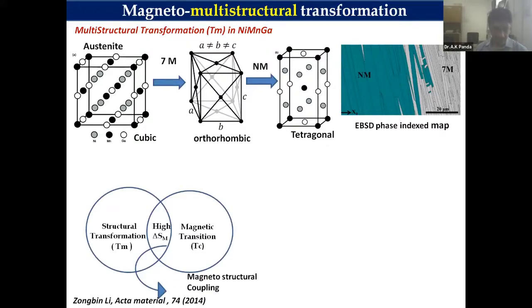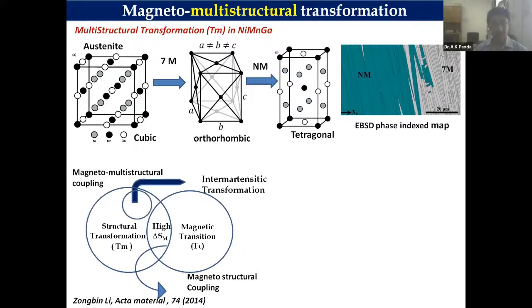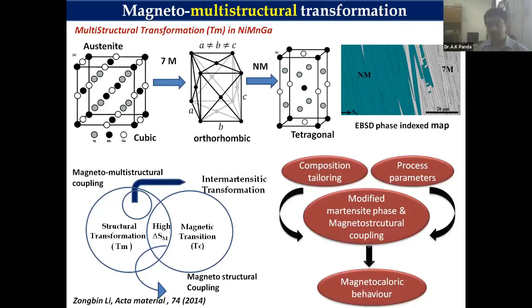When we talk of these materials, you can modify the structural things, because you can modify the combination of martensite as well. You can make a combination of martensite and austenite, and a combination of modulated and non-modulated martensite. Because of that, you can bring out a lot of modifications in the structure and consequently magnetostructural coupling. That leads to a very high entropy change.